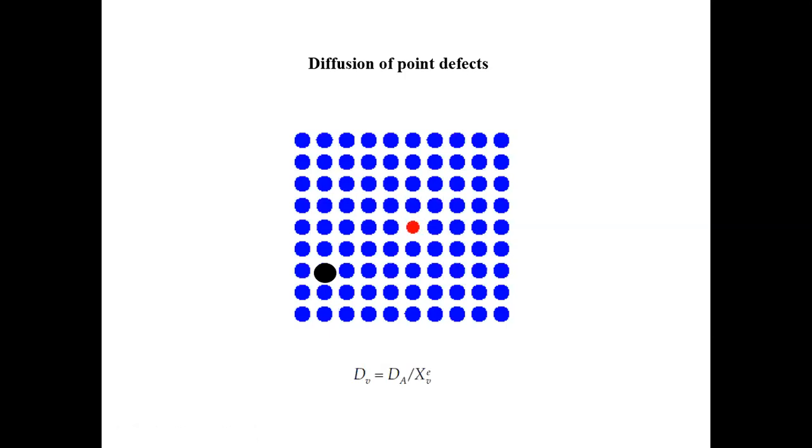Okay, so hopefully this explains this dilemma. So there's no contradiction here, right? They're the same mathematics describing the same processes. When you focus on the vacancy, of course, it moves faster because it's always moving. But if you look at a particular atomic particle, it can move when involved in one vacancy movement, but after that, it has to wait for a very long time until the next vacancy comes nearby. So that's where the vacancy concentration comes into the picture, and that's also the reason why the atomic self-diffusivity, or substitutional diffusivity, is going to be much slower than the vacancy, although they're the same processes.